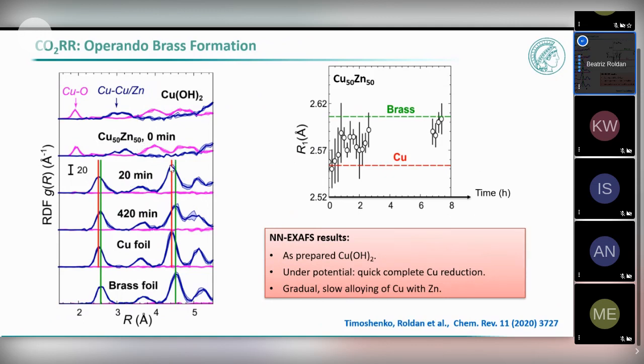This is when you have copper interacting with zinc oxide. But once we reduce the zinc oxide, we see a very clear shift here in the radial distribution function that indicates that we're making brass. You can follow here the interatomic distances, and you can go from pure metallic copper as a function of the reaction time to the formation of brass. So this in situ and operando spectroscopy data help us to understand the change in the selectivity. Brass makes CO and hydrogen. And if you have metallic copper in contact with zinc oxide, we can also make methane.